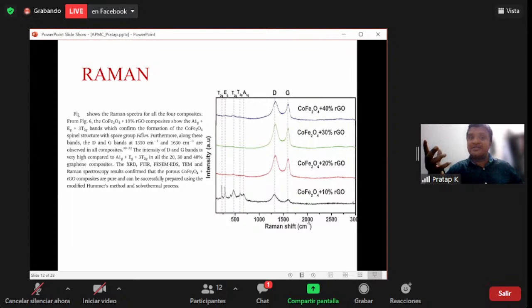But how do you confirm the graphene? Look at it. The black one is cobalt ferrite with 10% RGO, red is cobalt ferrite with 20%, green is cobalt ferrite with 30%, and this is cobalt ferrite with 40%. We haven't checked bare cobalt ferrite here, only these 10, 20, 30 and 40. All of these show the graphene peak, which keeps improving and shows prominently as the concentration increases from 10 to 40. So this clearly shows that our composite is graphene with cobalt ferrite.